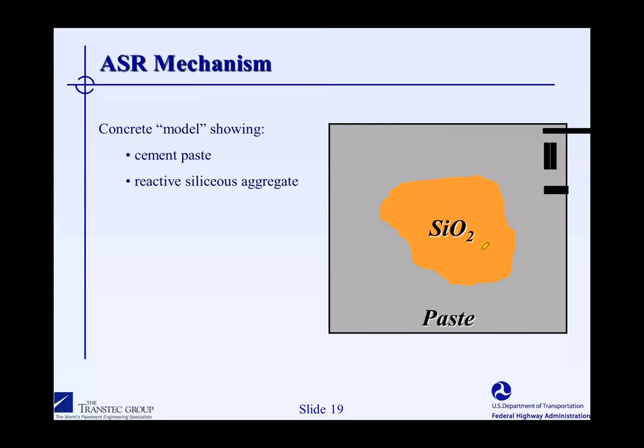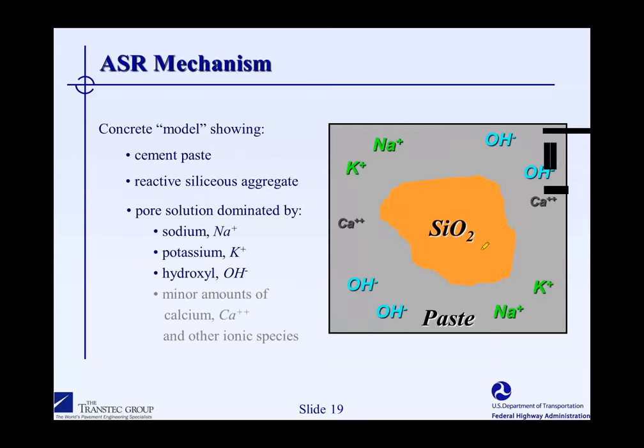We know that the cement paste of concrete is not a solid material. It is porous. It can absorb water. And when it's in a saturated condition, the water in those pores is very rich in ions, predominantly alkali ions, sodium and potassium, that's the Na and the K you see here, originating from Portland cement. And these are dominated by hydroxyl ions, OH minus ions. After one day, there's almost nothing else in the pore solution. There might be a little bit of calcium, maybe a tiny bit of silica, but after the first 24 hours of hydration, the pore solution is almost entirely sodium, potassium, and hydroxyl ions.